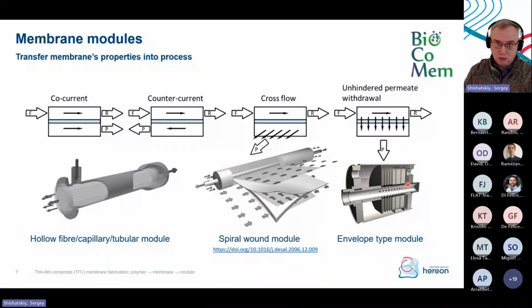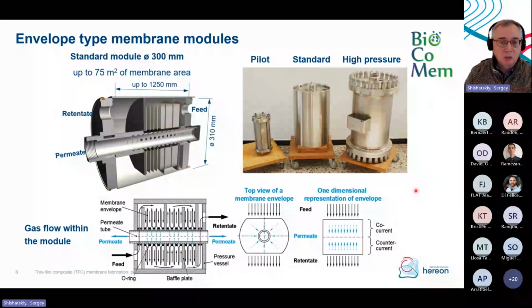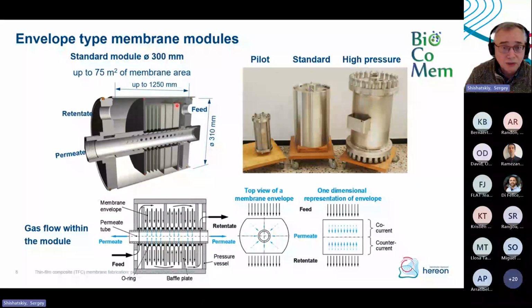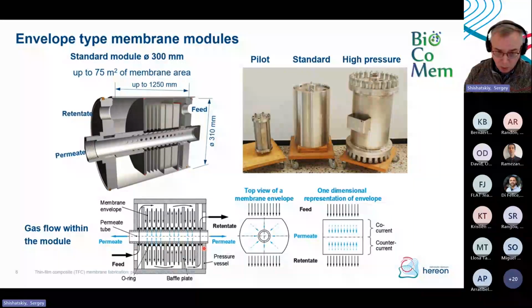And usually we produce quite high performance membranes, and we really need to know what is going on at the surface of the membrane, what the concentration polarization is, what the pressure drop inside the module is, and so on. So the module, you can see, consists of a lot of envelopes which are accumulated in compartments of different sizes. The size of a compartment, or number of envelopes inside the compartment, depends on how much gas we are pulling out of the feed gas stream, just to keep the linear velocity along the membrane element at a constant value in order to provide the best performance of the module.